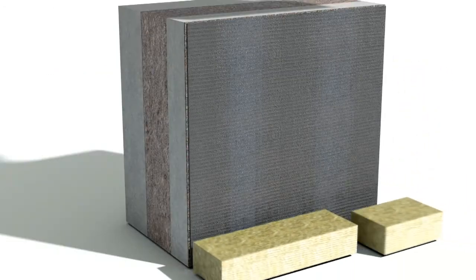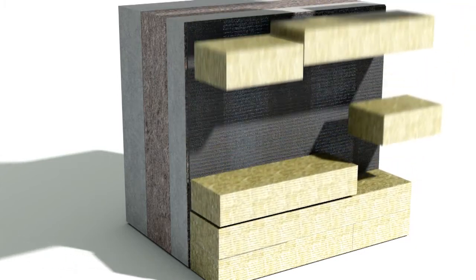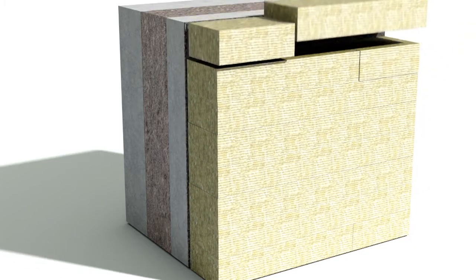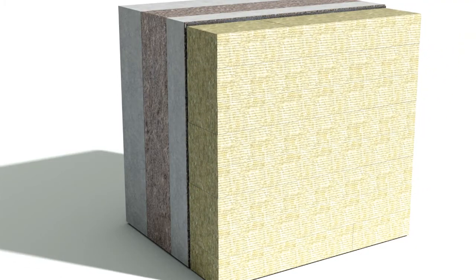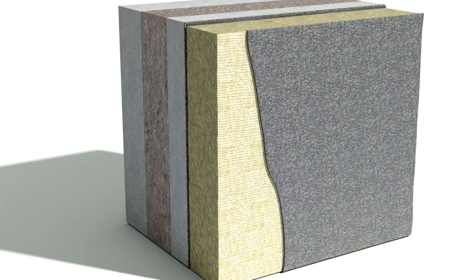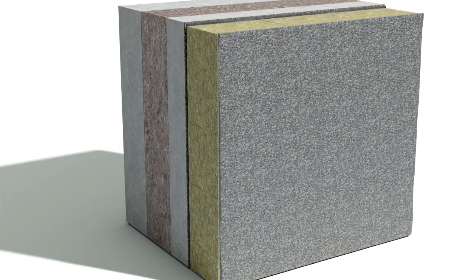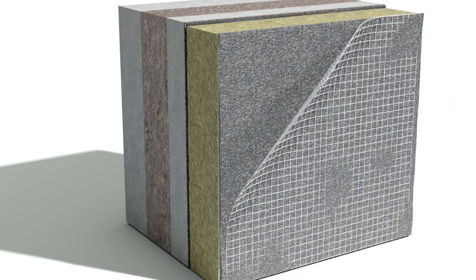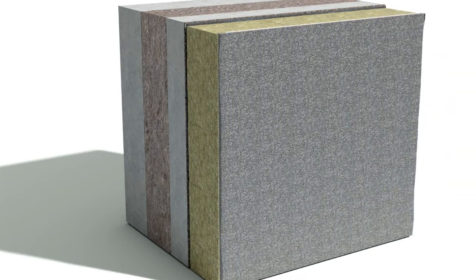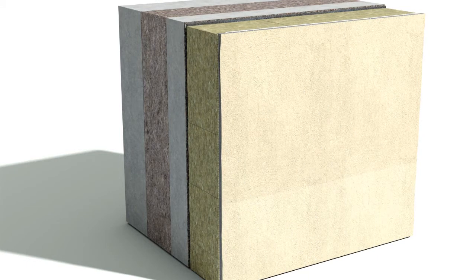Depending on the instructions from the system holder, in most cases no mechanical fasteners are needed. A thin render mortar is sprayed onto the surface of the alkali-resistant thermal insulation, into which an alkali-resistant glass fiber mesh is embedded, and on top of this a smoothing mortar and a surface mortar layer in accordance with instructions from the system holder.